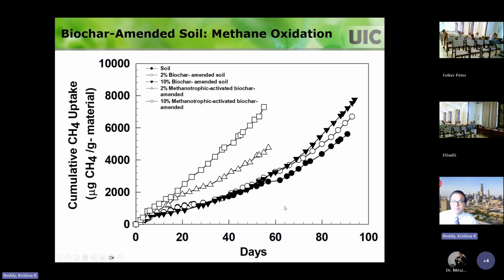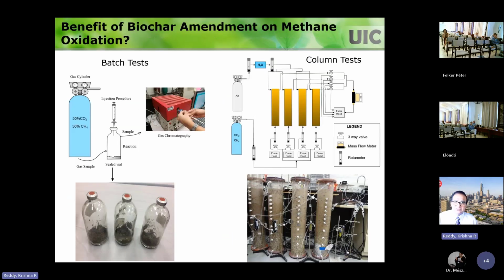And this can go on perpetually because there's no limitation on the capacity. It's just a biological process that keeps happening. So you can clearly see the benefit: if you have a soil, you can get the methane oxidation conversion into CO2, but it's very slow. But if I add biochar, we can really increase that to a higher capacity and higher rate. So that can be found from batch experiments.